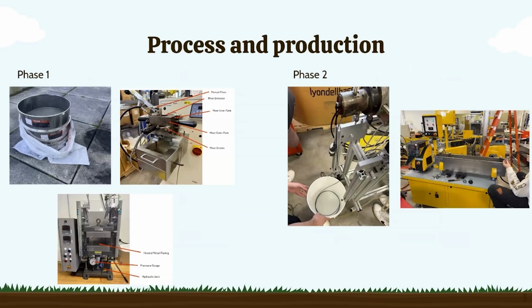So once we actually got in the lab, we split our production into 2 phases. In the first phase, we crushed up our biochar. We produced our 9 different compositions using a heated mixer and a heated press. And then we picked our favorite of the compositions based on testing performance from tensile testing, hardness, etc. And then in phase 2, we produced a larger batch of our favorite composition using the twin screw extruder, and then we pelletized that material.